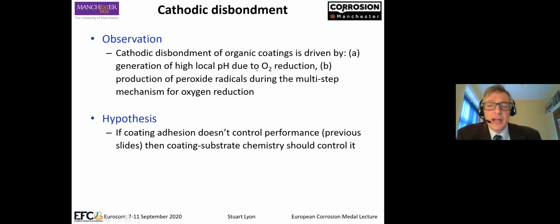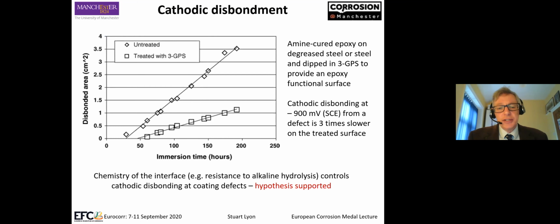So we need to be worried about the generation of high local pH due to oxygen reduction, and also the generation of peroxide radicals, which are part of the mechanism for the multi-step reduction of oxygen. Then perhaps if we create a coating substrate chemistry that's relatively resistant to these activities, we will get something that works a bit better. And we did. We used amine cured epoxy, and 3-GPS, which is 3-glycidyl propyl silane, an epoxidized silane. This is the cathodic disbonding rate for an untreated surface under the same conditions. This is the cathodic disbonding rate for the treated surface.